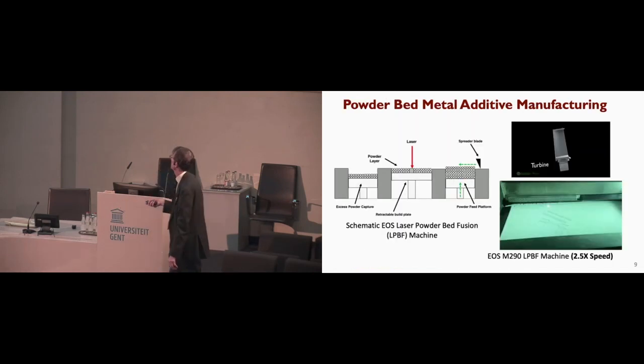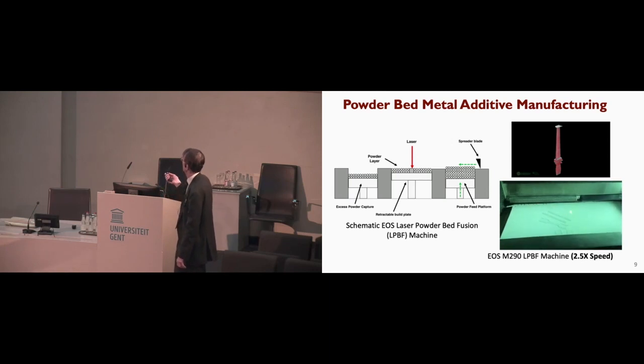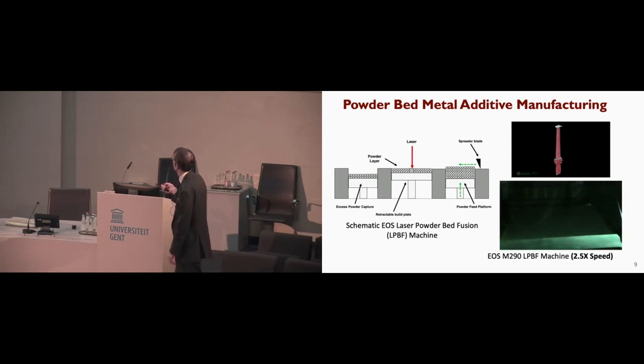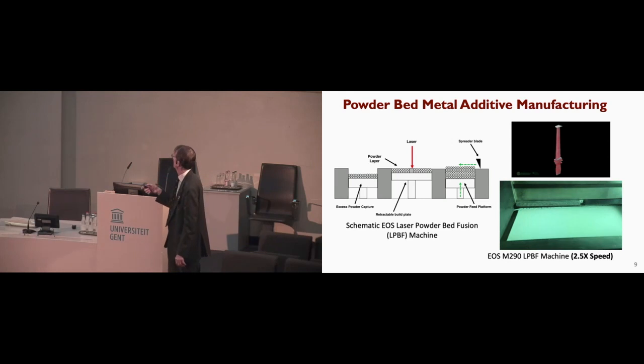So again, just to illustrate what many of you know, on the left is a basic diagram of how a typical powder bed machine is set up. Spread a layer of powder, use the laser to melt, not sinter, melt where you want it. The part is effectively sliced in the computer, and then you fuse in place each layer, one layer at a time. The actual process looks something like this if you peer in the window. Perhaps the most notable thing is that as the laser is melting, there's a lot of what looks like a sparkler to me. There's a lot of stuff going on, so we'll come back to that in the visualization.